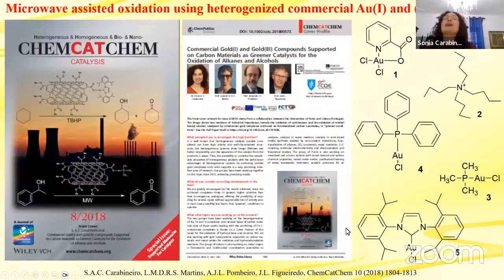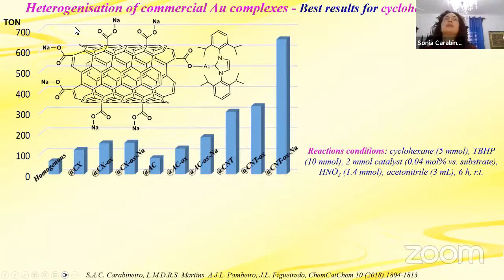And we also tested the microwave-assisted oxidation using heterogenized commercial gold complexes. So these were the complexes that were used. They are commercial complexes. We did not need to synthesize them in the lab. So we just anchored them on the carbon materials. And this was also a cover of this special ChemCatChem issue. And it had also a cover profile with a small interview to the authors. And the results were also interesting.